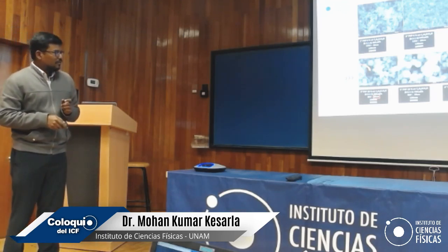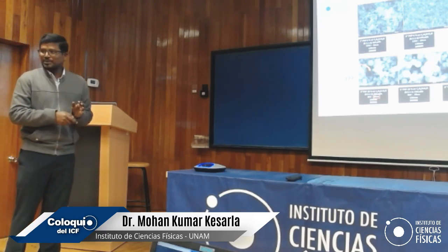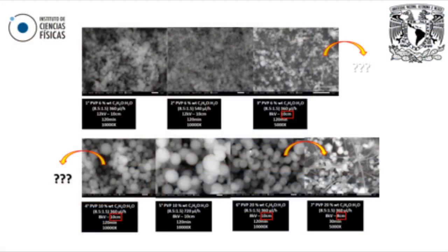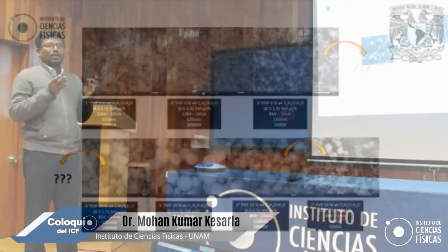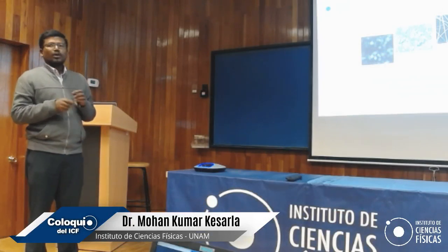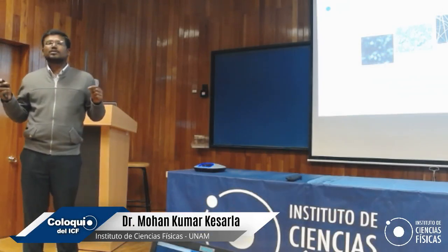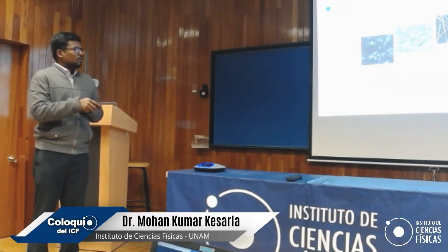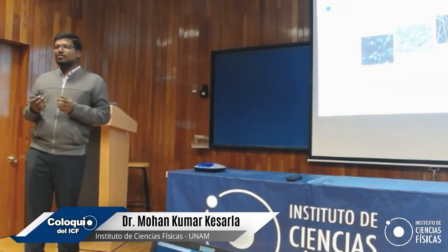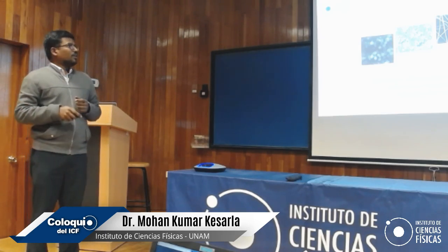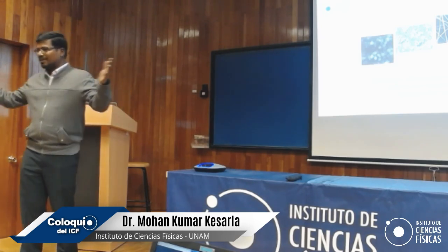Very, very important. And finally, Dr. Ivan tried to get some fibers, and he found some fibers with process parameter control. So here the process parameters are quite important. If you look here, the process parameter is only concentration. If you use a low concentration, you are going to get polymeric nanoparticles instead of polymeric fibers. If it is intermediate, you are going to get spindles along with the fibers, which is not good. To have the desired fibers, you need good control of the process parameters for sure. If it is excess, you can get the